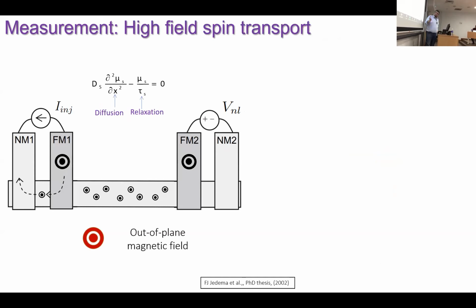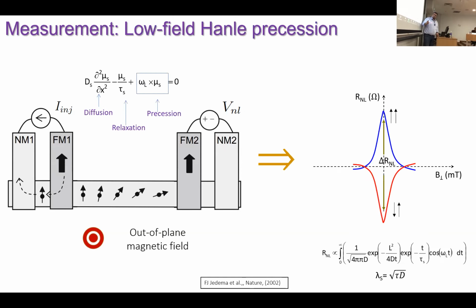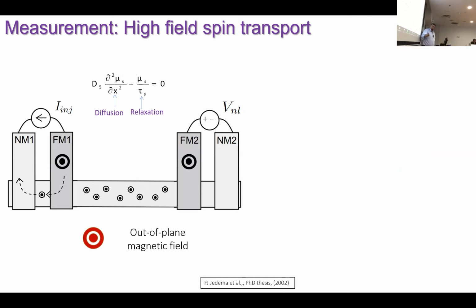The third measurement that I will be showing you today is this: you again apply the out of plane magnetic field, but this time you apply a very strong field. In the previous case, we were applying quite a small field, and the magnetization direction of the ferromagnets was still in plane. But if you push a bit more, applying much higher fields, then these ferromagnets will have out of plane polarization. Therefore, whenever you have the spin current propagation here, the spins are pointing out of plane. This is different from the previous measurement, because there the spins were precessing in plane. So by doing this experiment, you can get information about what the spin properties are once spins are aligned out of plane versus in plane, right?